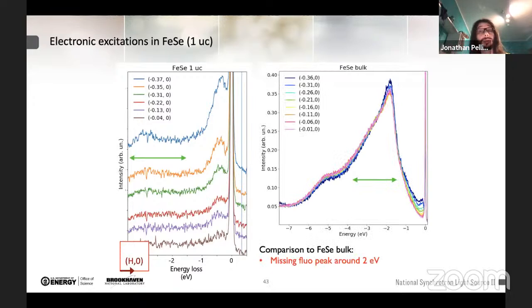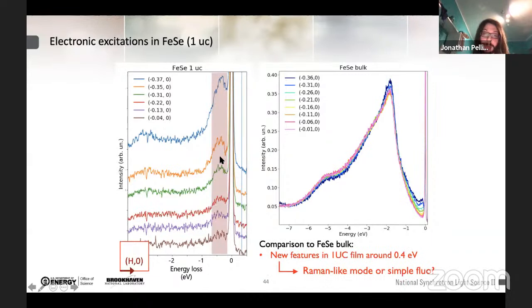So if we look in the high energy loss region from minus 1 eV up to 3 eV, we can see that we have a much weaker fluorescence line compared to the bulk case. But more importantly, we have a pretty strong peak at around 400 meV, and this peak doesn't disperse and change energy as a function of momentum. In fact, this peak is essentially a flat mode.